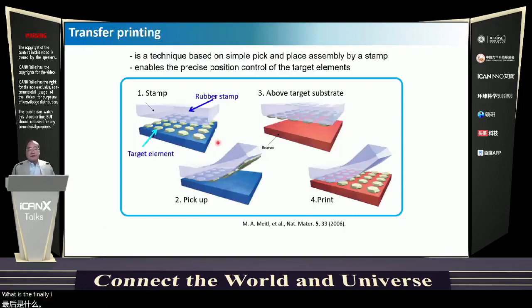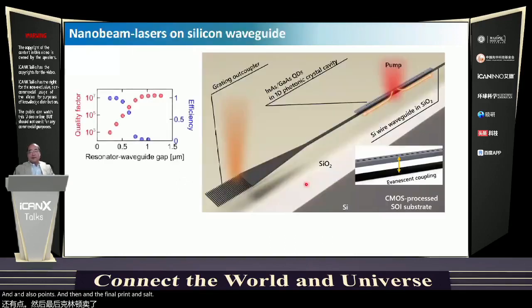Okay, so finally, I briefly mention the transfer printing method. This is a technique based on simply pick up and place assembled by a stamp. This enables the precise position control of the large target elements. And this is the process: stamp, pick up, and alignment, and also position, and the final print, and so on. Indeed, we try to place nanobeam quantum lasers on the SOI silicon waveguide. And here, there's a gap defined by silicon dioxide.